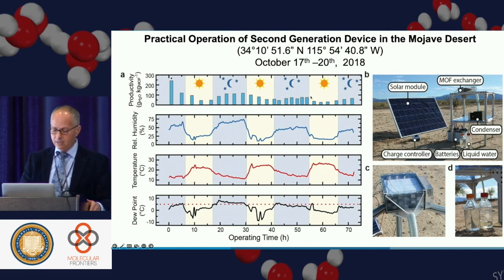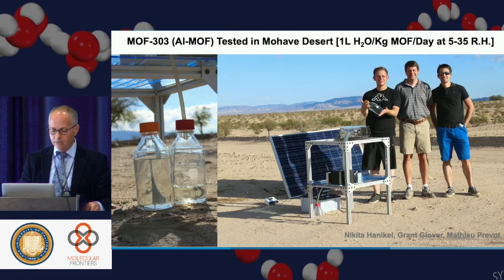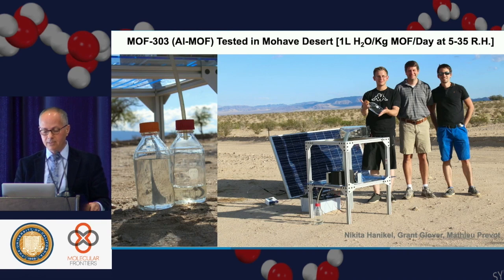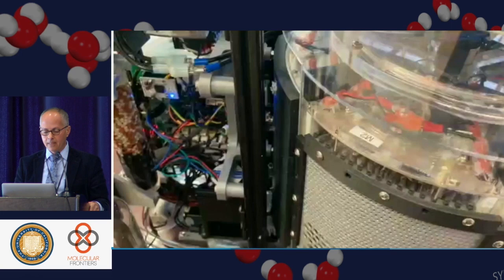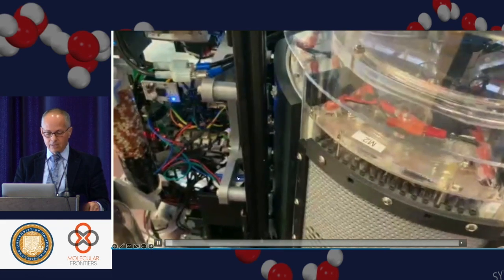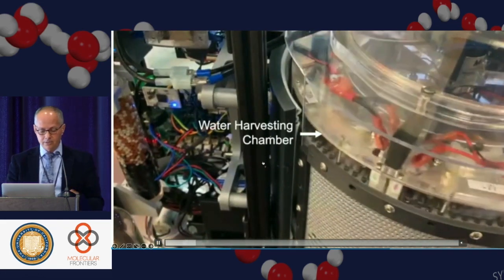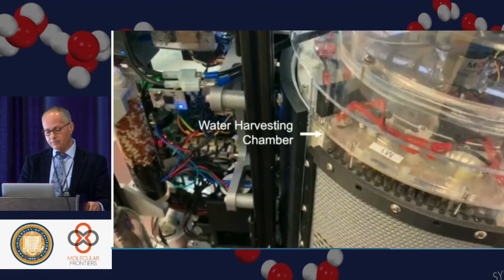In this case, we interface the device with a solar panel to allow for power to push air through the material so that we can do more than one cycle, not just day and night, but more than one cycle during the day. So the students harvested 1 liter of water per kilogram of MOF per day under those conditions. And the water is pure, the MOF works very well, and now we have completely electrified the system and made a prototype together with our startup.